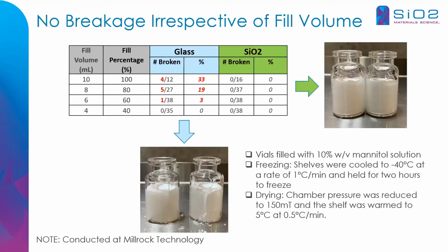Moving on to breakage. This was a study that Millrock Technology conducted, where we looked at vials with 10% mannitol, put onto freezing shelves at -40°C, and then cooled at a rate of 1°C per minute, then held for 2 hours at freezing. And then the pressure was reduced to 150 millitorr, and then the shelf was warmed to 5°C.